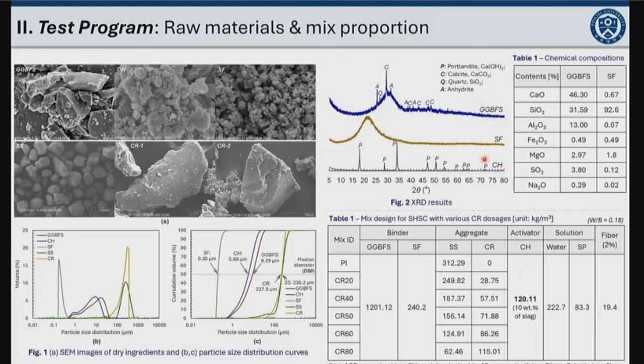The XRD patterns of the slag and silica fume show that they have high amorphous phases with small quantities of crystalline minerals. Also, the size of crumb rubber was quite similar to that of silica sand.